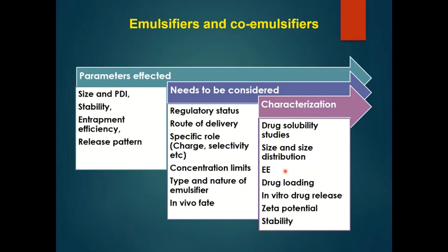And finally, in vitro drug release. So sometimes what happens is if you use a higher concentration of surfactants, you may get very beautiful particles with a very small size like 50 nanometers, 40 nanometers. But in that case, these can give you a burst release. Why? Because a high concentration of surfactants, once you put it into the dissolution media, will allow the drug to release very fast.